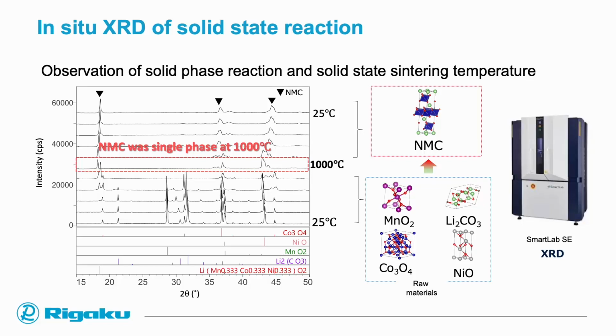On the other side, when we are interested in the solid state reaction of our raw materials, for example here, again in the case of NMC, we can perform so-called in situ XRD experiments for the solid state reaction, where we can directly observe the transition from raw materials, from precursor materials to NMC, in this case around 1000 degrees C. For that, of course, we would require a bit more sophisticated equipment. For example, in this case, our SmartLab SE, a floor standing device, because we would need to attach more sophisticated sample attachments on our diffractometer, which we are not able to do on our benchtop devices.